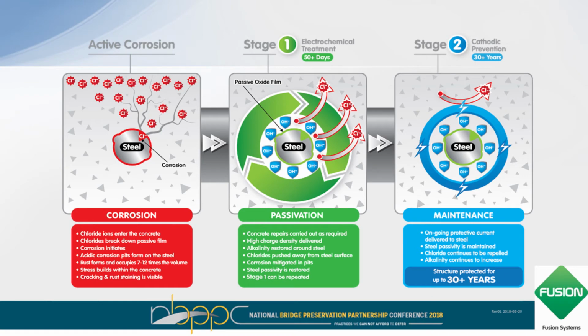So the higher chloride contamination you have to get to the passive stage, that's important information to have when these systems are being designed. But it may take, in this case, 50 days potentially. But that automatically switches over to a galvanic cathodic prevention phase, which basically is just providing enough protection to the steel to hold the passive nature in place, and that'll stay and basically extend the life of the anode life could be up to 30 years in this situation.